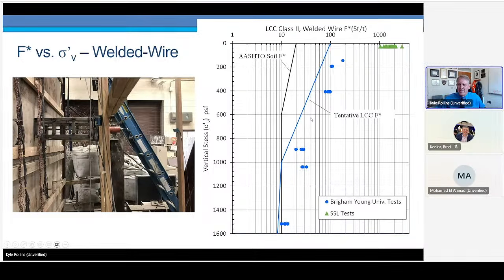So this shows the blue dots are the F star values that we had. Here's a tentative design recommendation with linear segments. And these are the BYU tests in blue. These are the tests from SSL company that they did in connection with a Caltrans project. And you're seeing that there's a tendency for the F star to decrease with increased confining pressure. Near the surface, down to 1,000 PSF pressure, we're getting higher F star normalized by the spacing here compared to what we'd get for soil if you take 20 feet and multiply it by the unit weight of the LCC concrete.